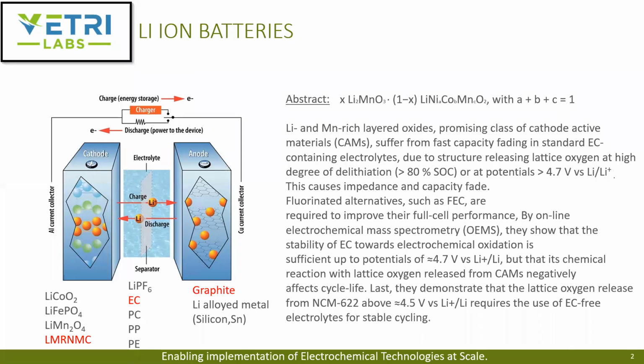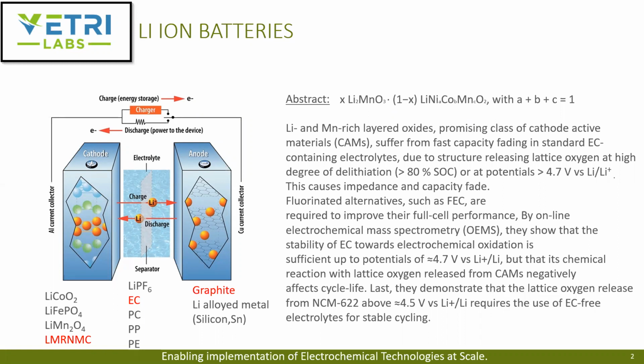This has been attributed to several mechanisms, and this publication deconvolutes several mechanisms through multiple studies, finally honing in on the cathode active structure releasing lattice oxygen at a higher degree—greater than 80% SOC, or at cathode potentials greater than 4.7 volts with respect to lithium plus—which causes higher impedance and capacity fade.